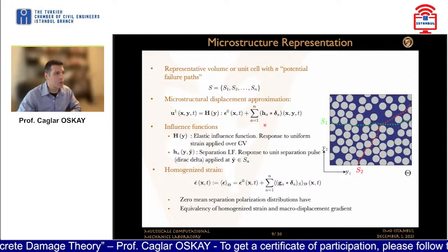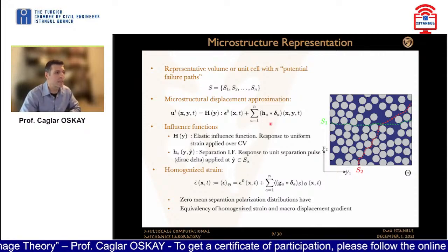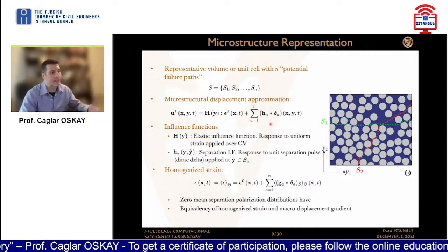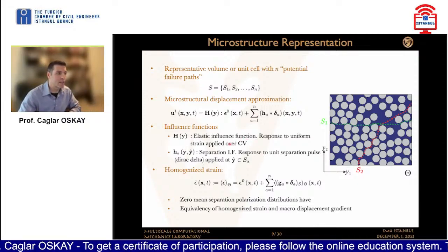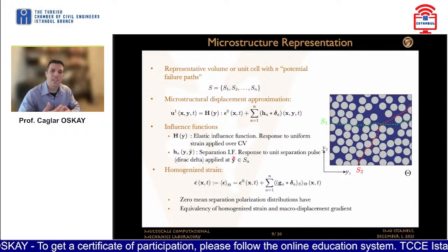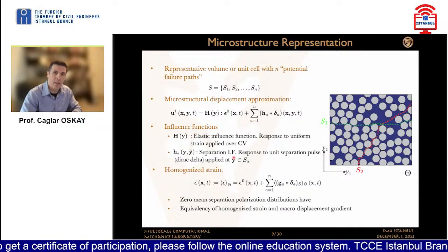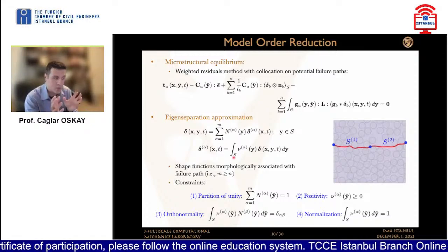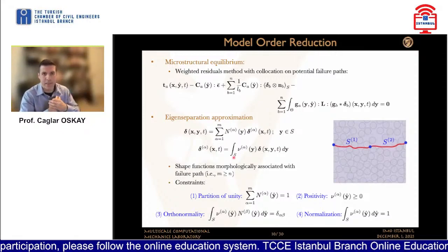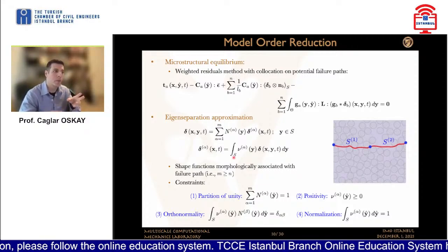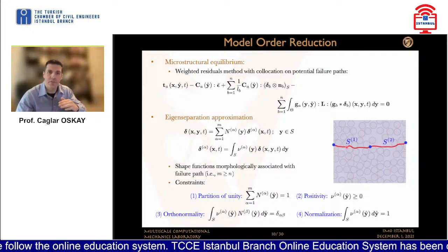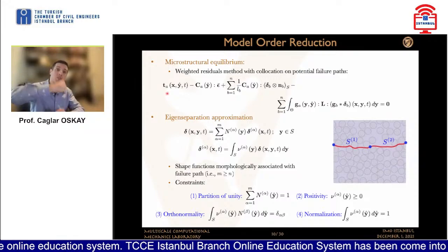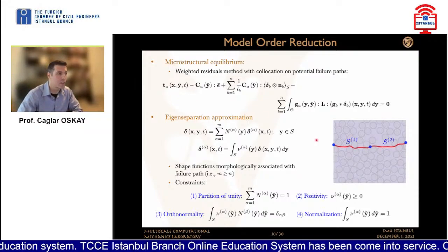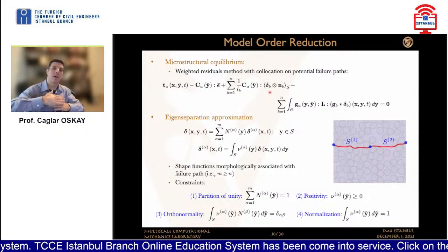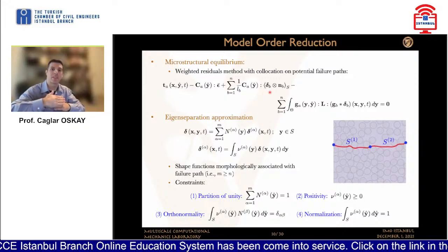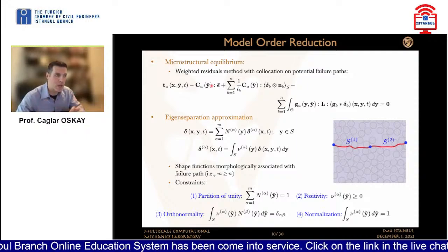So then we continue with a microstructural displacement approximation that allows us to write it in a form that takes advantage of what we call the elastic influence function and the separation influence function. These are Green's functions that you can solve offline very quickly using linear elastic analyses defined over the microstructure. Then we do a little bit more math to bring the microstructural equilibrium, expressed only on these potential failure path surfaces. The T here is traction, the forces on those potential failure paths. Delta is the separation. That is how much that crack, or that potential failure path, is separating under the loads. Epsilon bar is the macroscopic strain state, and so on and so forth.